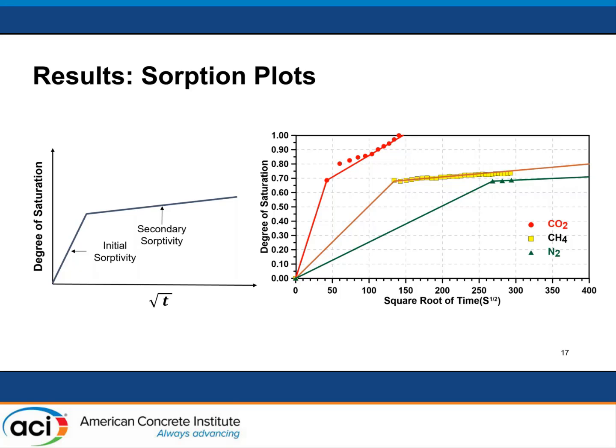So when they were empty compared to as the water filled each of these, I was able to do a volume fraction to determine and make these points and plot the secondary sorption for each of these over that 24-hour window. And so there are 3 main takeaways from this plot. One, the CO2 filled voids became completely saturated almost nearly when the methane filled samples started to just fill with water.